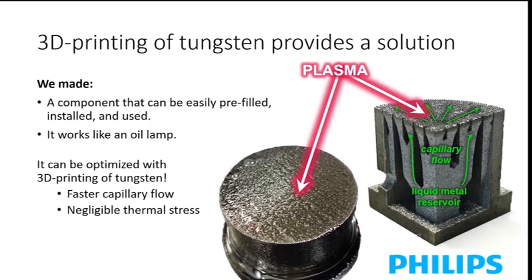So this works great. And what's even better is that because we can use 3D printing, because of course there are other ways to make solid porous materials, but with 3D printing, you can really control very well the internal geometry of such a sample. So you can maximize capillary flow, and you can reduce thermal stresses due to heating, thermal expansion, bending. You can reduce those stresses to virtually negligible levels. 3D printed tungsten is not as strong as regularly manufactured tungsten. It has about half the strength, let's say, but it's absolutely irrelevant because the stresses are also irrelevant.